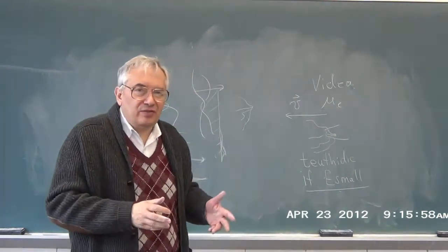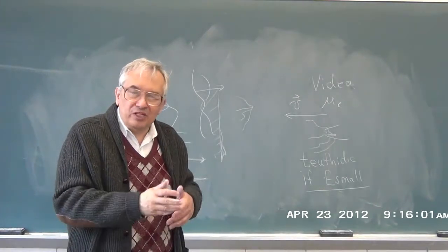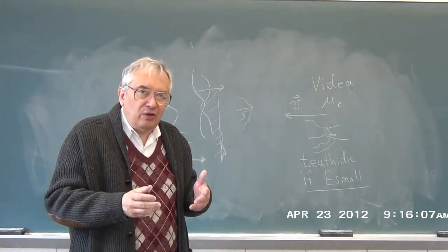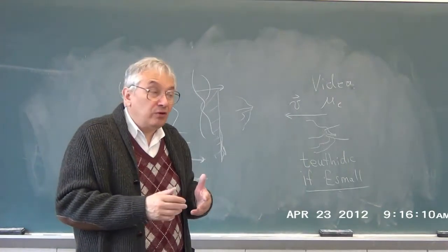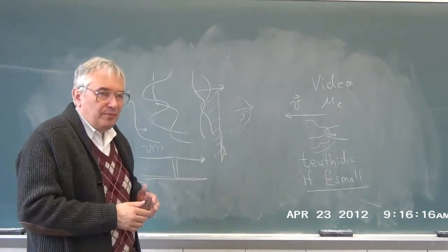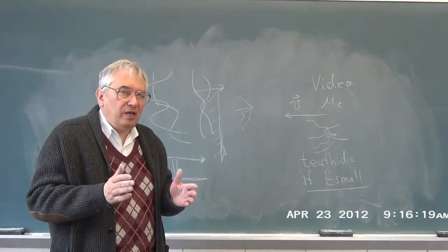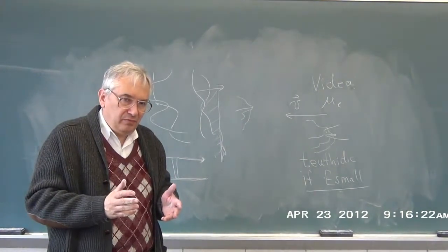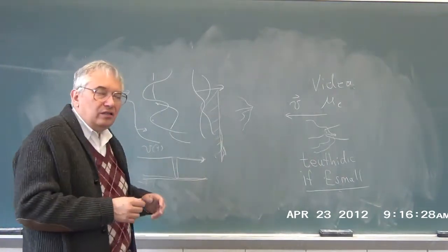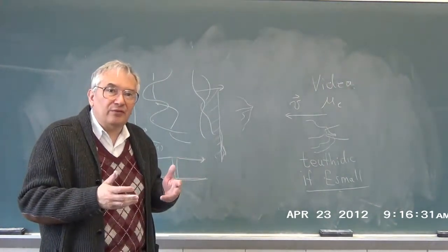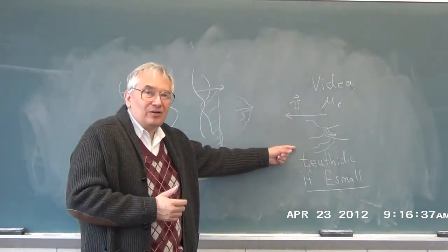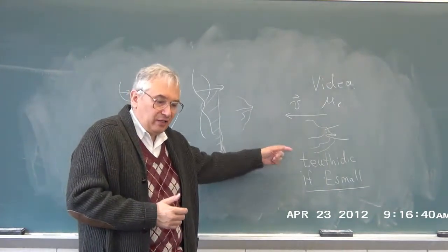Now, of course, the two chains, if they're the same size, are co-equal, so there'll be some compromise on what they do, though when they're very close, they will have very much the same random thermal forces on them. The assertion that both chains stop when they collide is the fundamental basis of the tube model, of all of the tube reptation models. The assertion that they drag along is the fundamental basis of most of the hydrodynamic models. This experiment is the critical test for determining which model is correct.